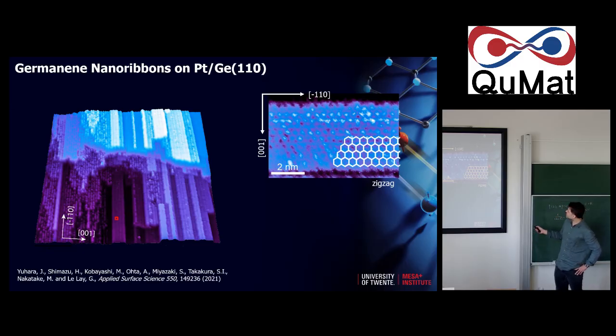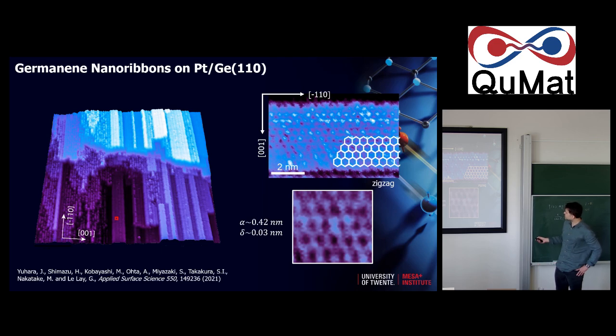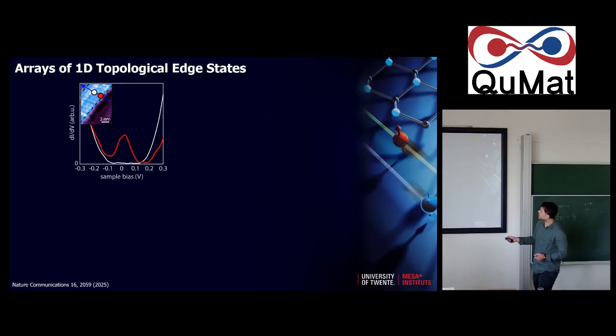So this is germanium. If we look closely with atomic resolution, we see that again it has a honeycomb lattice, similar to the 2D layer. So you have this honeycomb structure, lattice constant about 0.42 nanometer, just like germanene, 2D germanene, and the buckling a little bit smaller, at least what we can extract from the STM data. So we think that these are indeed germanene nanoribbons, and then you get these parallel arrays next to each other and so on. So to check that, we wanted to look at the electronic structure of this with scanning tunneling spectroscopy.